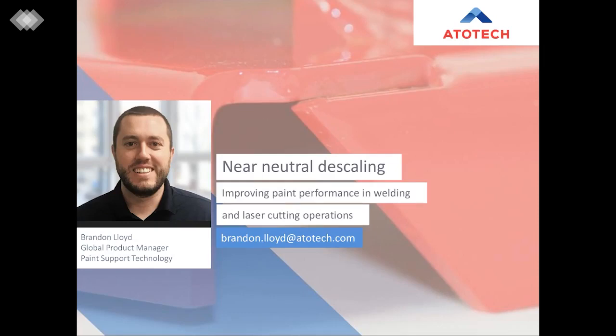Okay. The bath life is really a metric that is dependent on several factors of a customer's application. The first is probably the production volume. Much like with other chemical processes, more production results in quicker use of the solution's usable life. Also, the throughput in relation to the solution volume will play a large factor in the bath life. So for instance, if you have a very high volume of production and a small tank volume, then the bath life of the chemistry would be much lower as compared to an application that has a smaller throughput with a much higher bath volume.